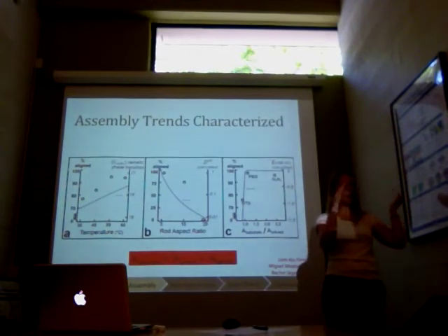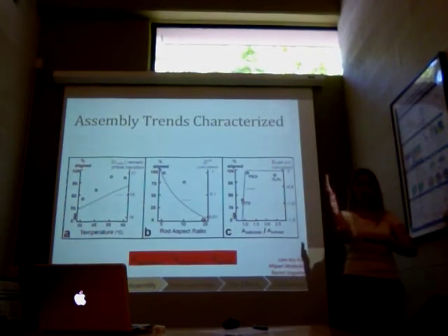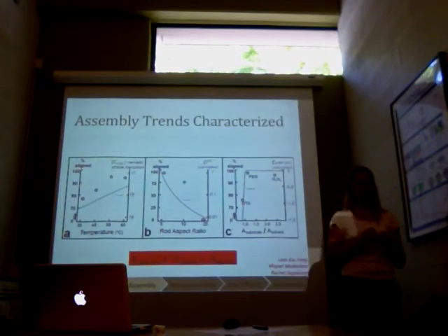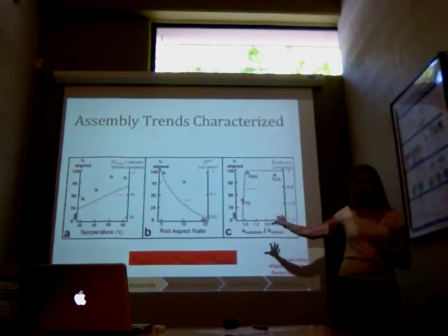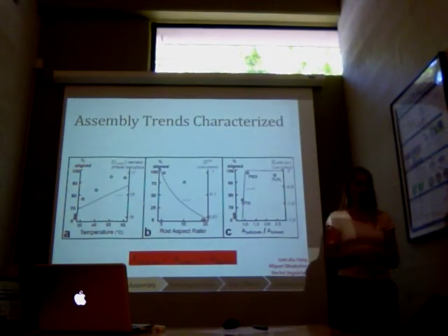film, which isn't that much. It starts off as 30 nanometers, so it's pretty small to begin with. But a lean of 20 degrees is very acceptable and not so noticeable to the film. Once we get past 20 degrees, it's going to start decreasing the thickness of the film pretty quickly. And this is already a concern. We would need to have pretty extensive light trapping in a system that's 30 nanometers thick to begin with, but if we get it down to 10 nanometers thick or something, we'll have a problem.